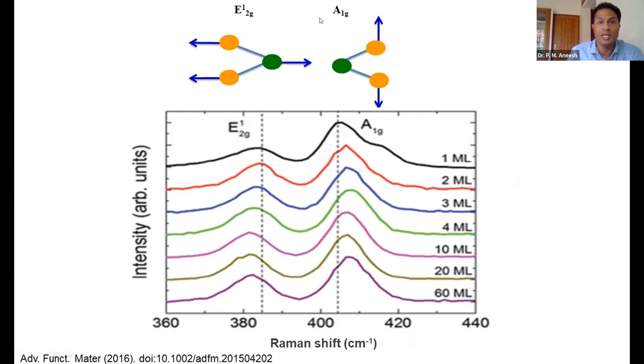So these are the two peaks, and you can see that there are two vibrations. One is E12G and another one is A1G. E12G means the sulfur atoms are vibrating towards the left side, whereas the molybdenum atom is vibrating in the other direction. So these vibrations are opposite to each other. Whereas the A1G peak corresponds to the sulfur atoms vibrating in opposite directions. The A1G peak is this one and the E12G peak is this one.